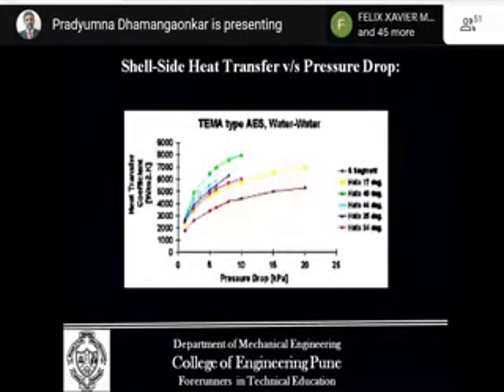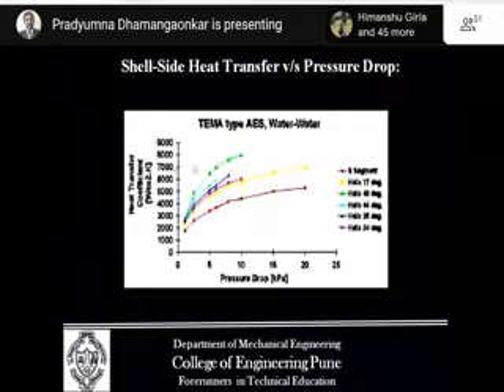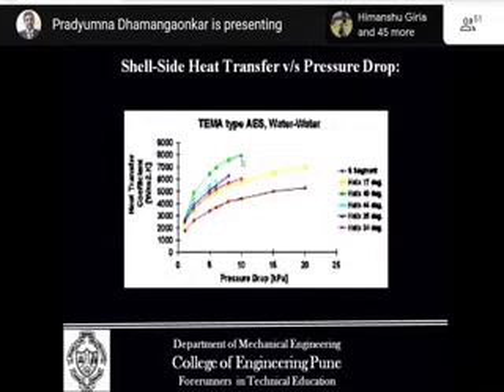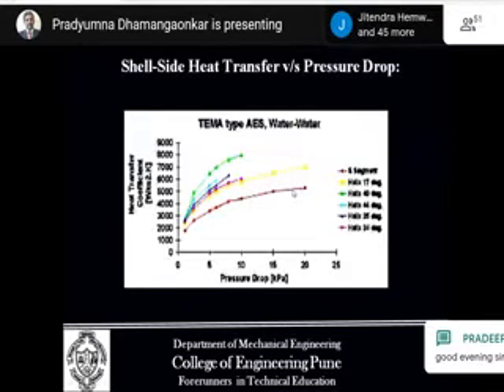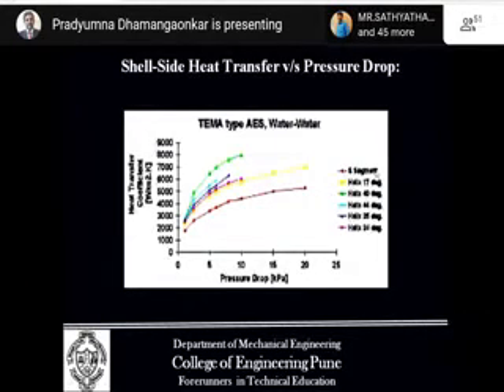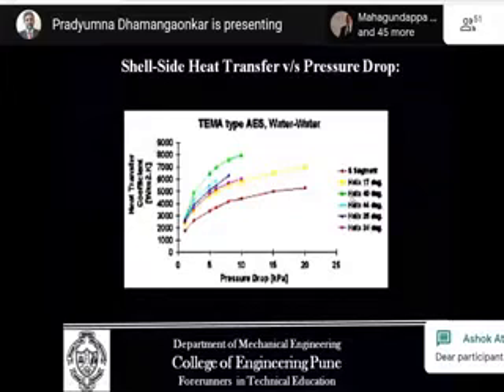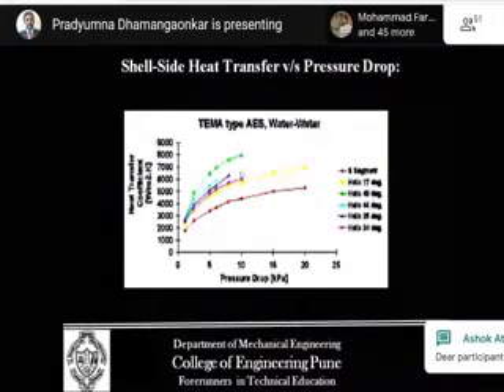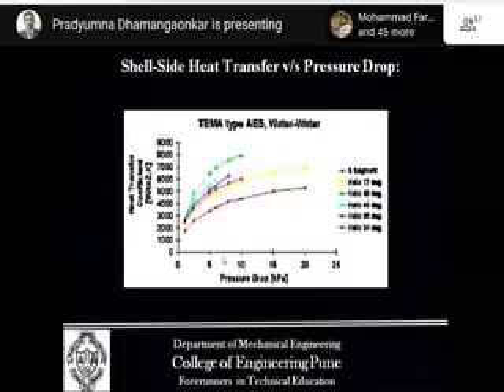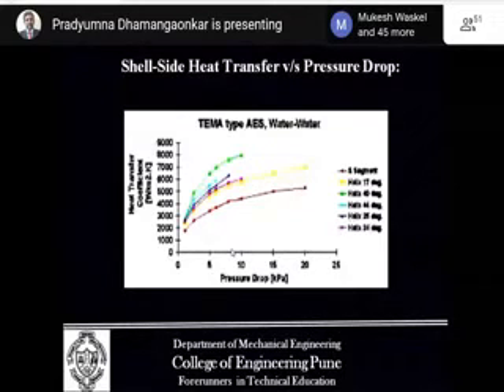If we look into this graph, this green line is giving the highest heat transfer coefficient, and at the same time, its pressure drop is also less as compared to this yellow, which is at 17 degrees, and this brown, which is nearly straight. So it is preferred to go for the helix with 40 degrees. This will give us a higher heat transfer coefficient as well as a lower pressure drop. In the helix changer, these baffles are placed at 40 degrees with the vertical, and this is what the helix angle is called.